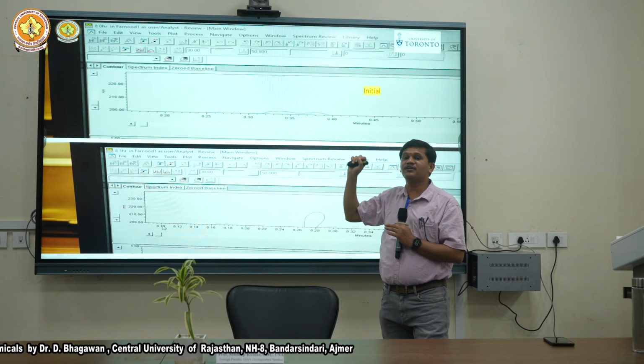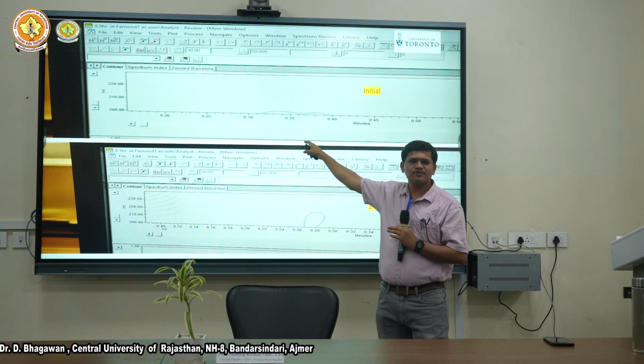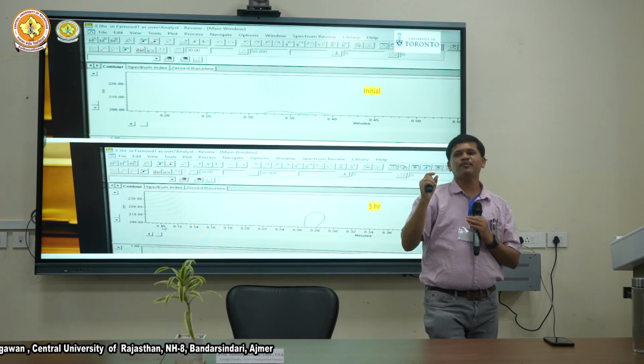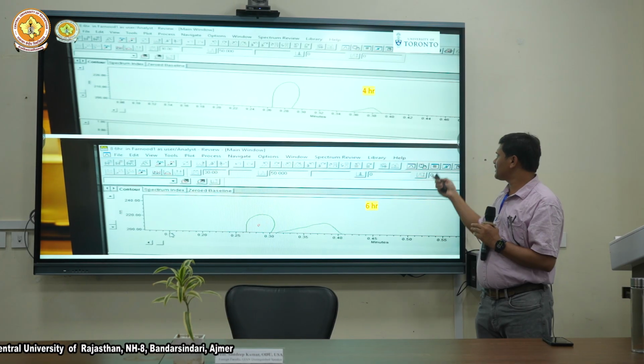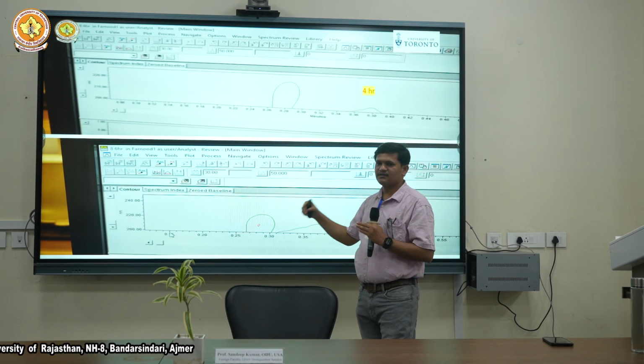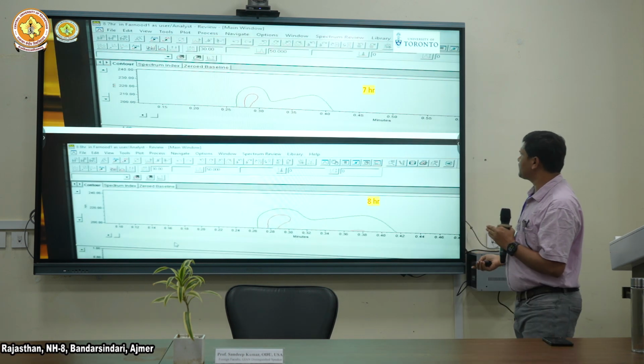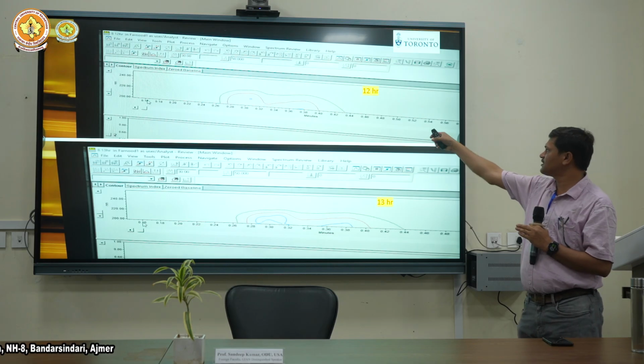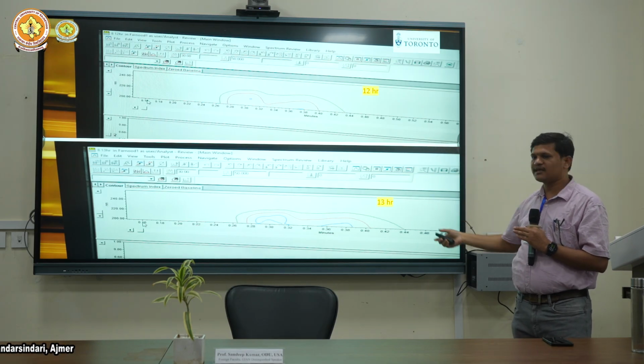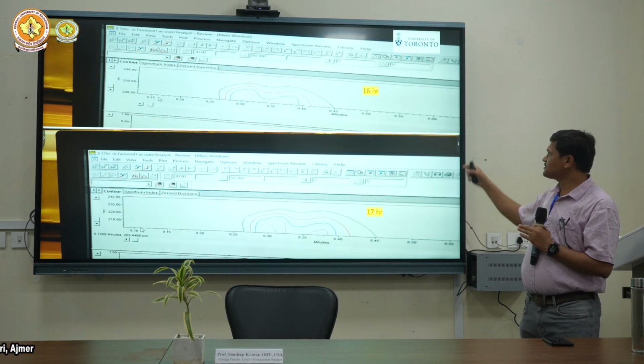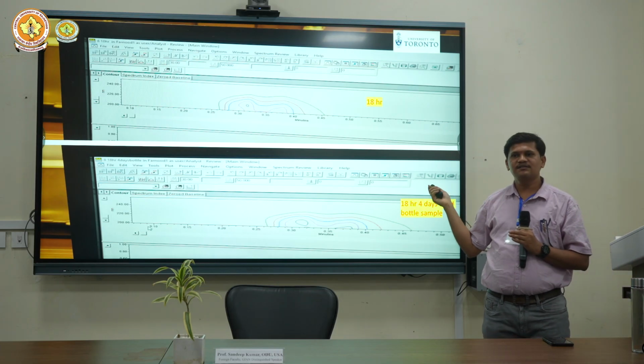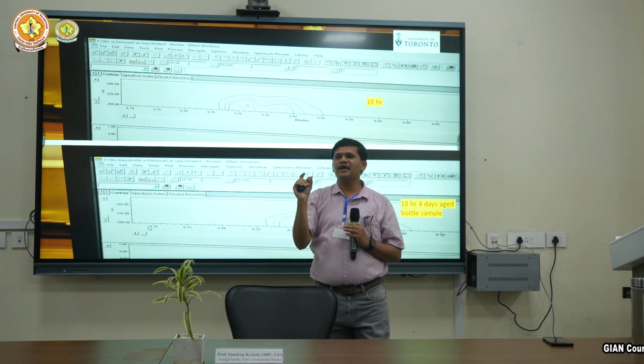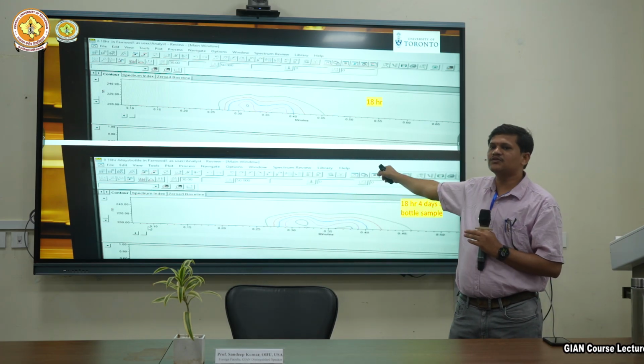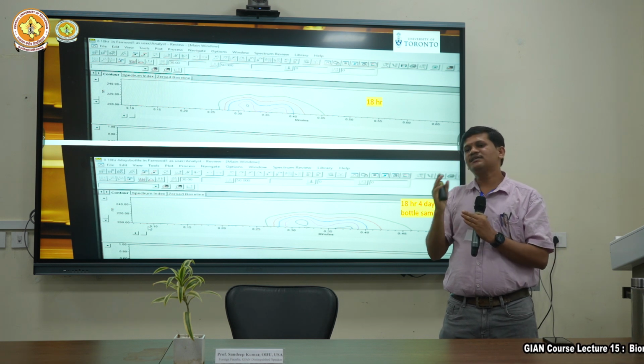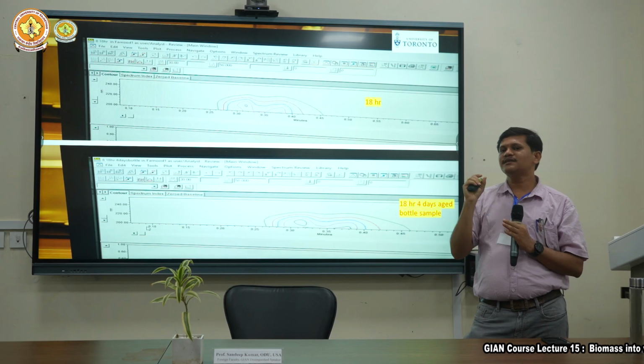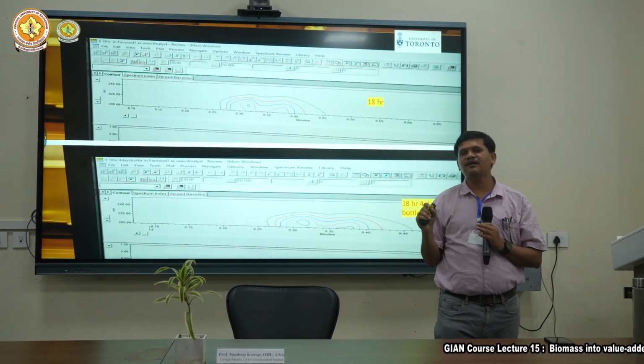This is the initial one, without photocatalytic reaction, where the new compound formation has been identified, and the next one shows the increment of that particular compound at the same site. With increasing time intervals, you can see the concentration has increased, and the same thing continued up to 18 hours. Here you can see we have 3 layers, and this is the extended 3 layers, up to 18 hours. You can see the new compound formation at the same retention time, which indicates that oxidation of the lignin is taking place, and we are getting a selective compound. This mechanism we generally call selective oxidation of that particular compound.